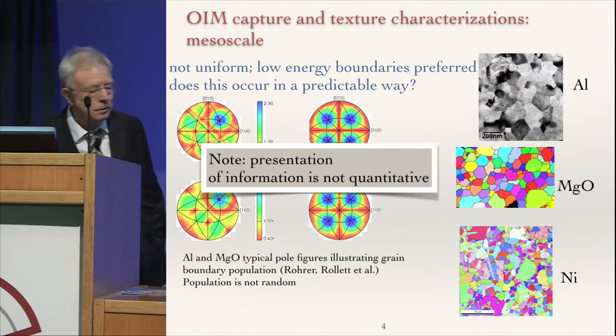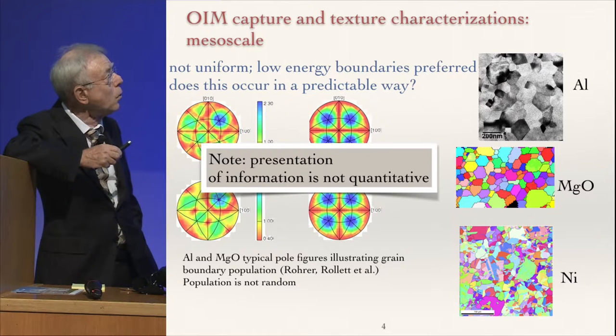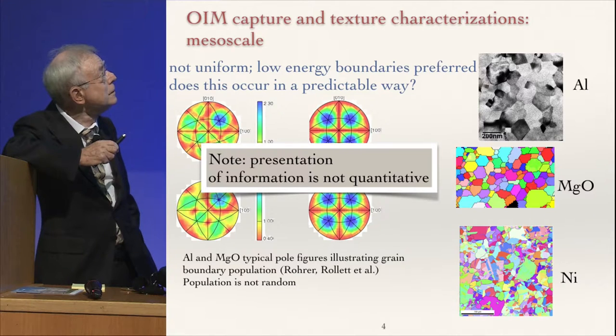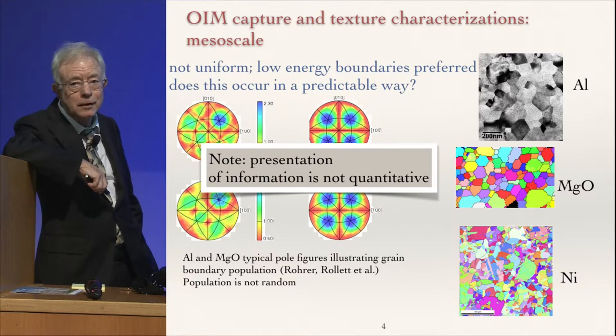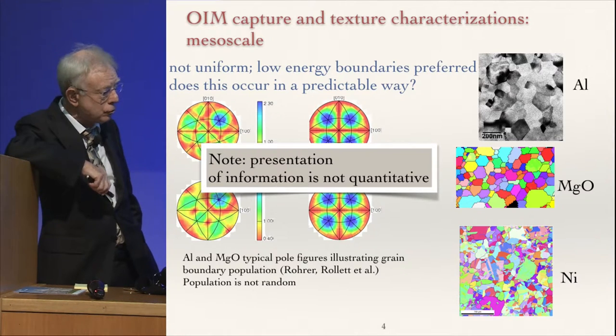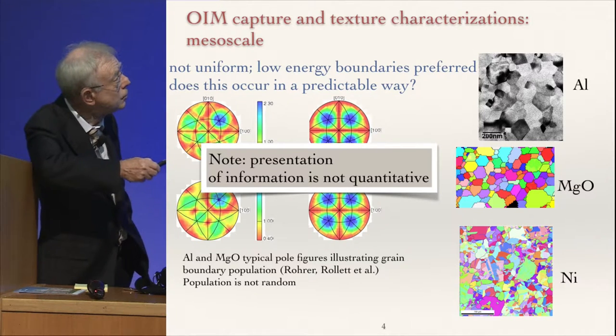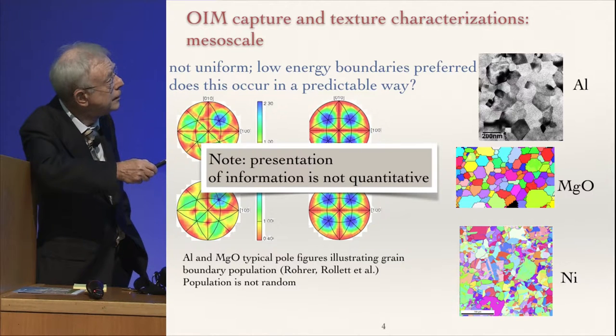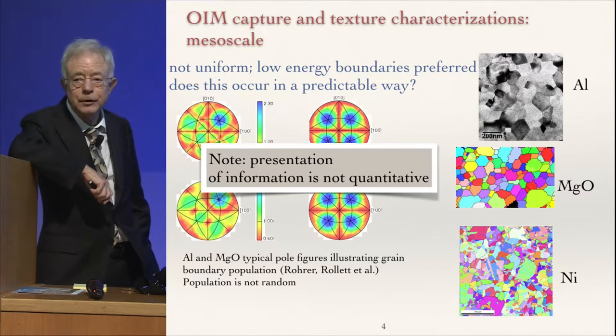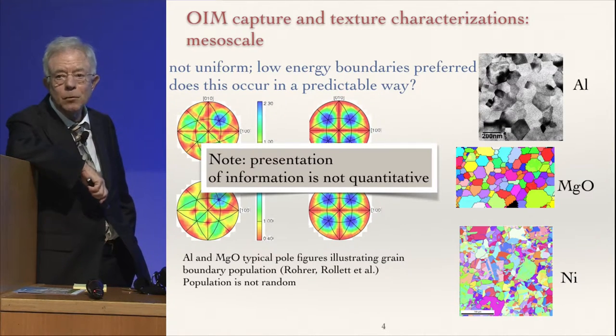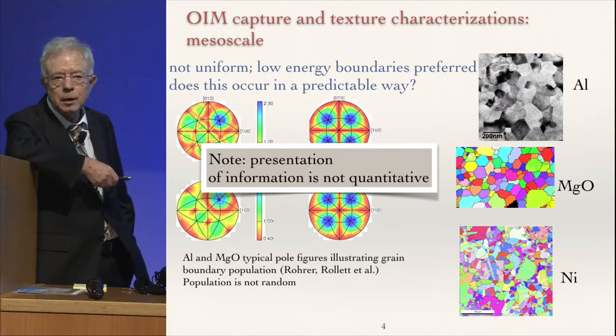And the other feature of this picture is that this is, in fact, the way it's presented to us, and you can see that it's not quantitative. It's simply not quantitative. If you imagine how you would characterize a grain boundary, not the grain, but the grain boundary, you would characterize it by perhaps the normal direction of the grain. Let's just look here at one of these. The normal direction and the lattice misorientation. Namely, these are elements of a cubic lattice, and to go from one to the other would be a rotation. So altogether, there'd be five variables. Here you're looking at two. One of them is chosen in advance, but the others are averaged out. So what do you think you could do with that kind of information? Well, maybe you can process the material to some extent, and that's it.